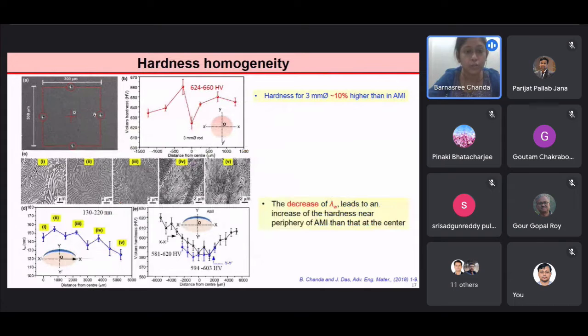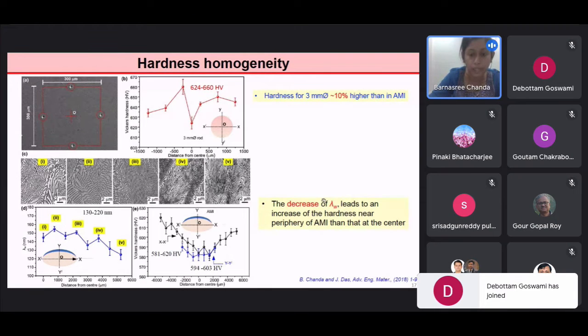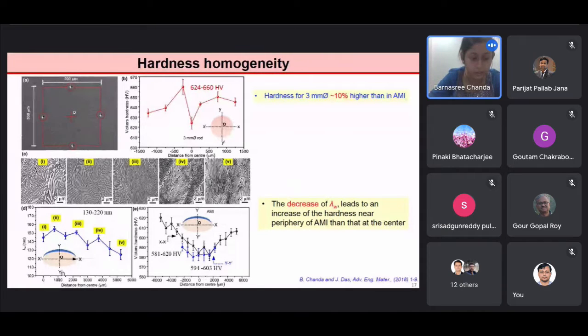Figure A shows the hardness profile adopted for the measurement of the hardness at a single point, and figure B shows the hardness profile across the x direction for the 3 mm dia suction casted rod, where we see that at the center of the specimen, the hardness is lowest, and the hardness varies in the range of 624 to 660 HV. Figure C shows the SEM image of the lamellae variation from the center to the periphery of the arc melted ingot. And when we measure the lamellae thickness, we get a trend.